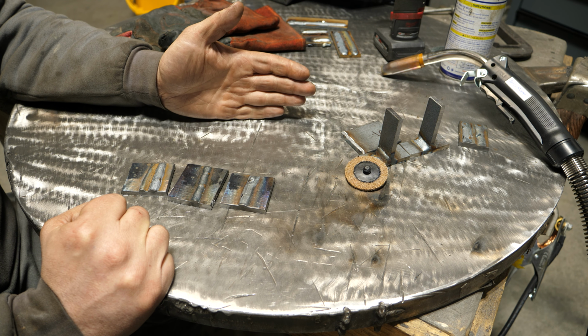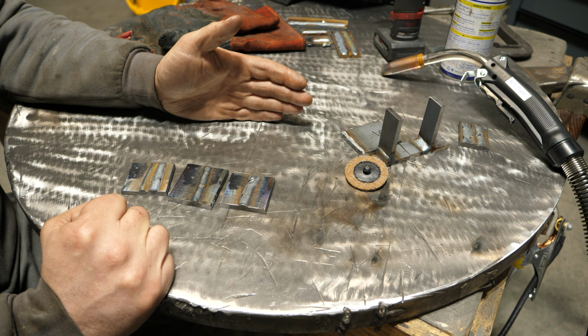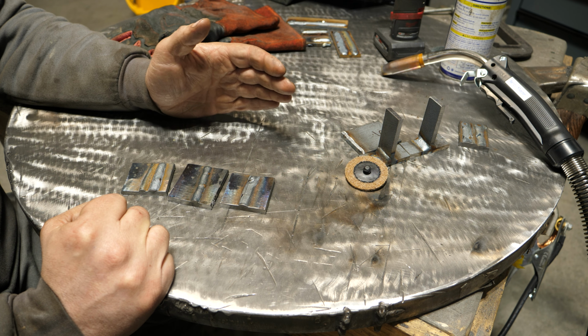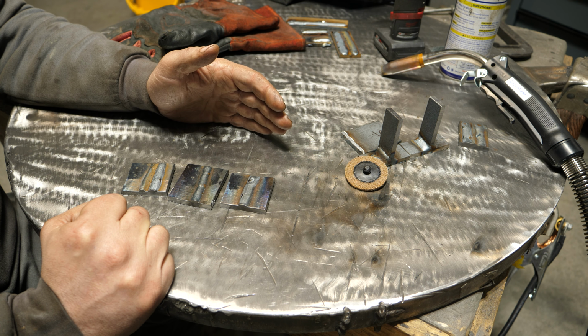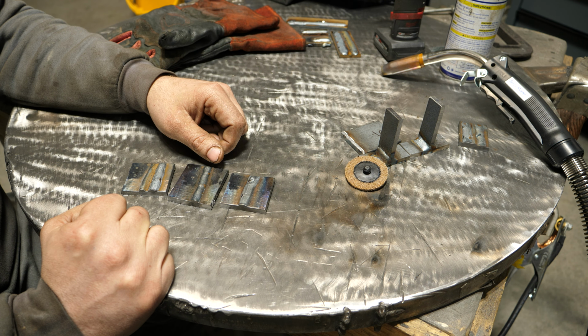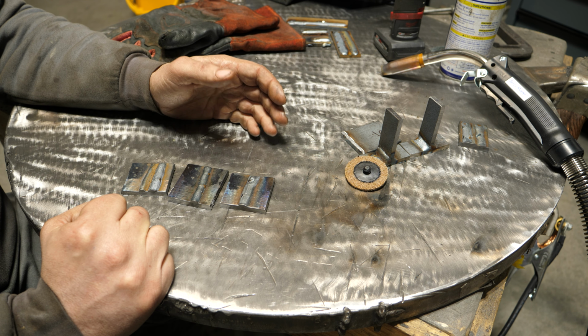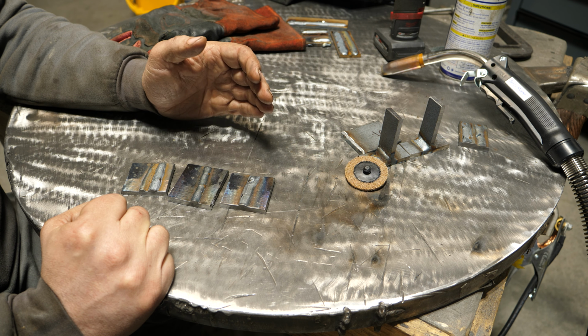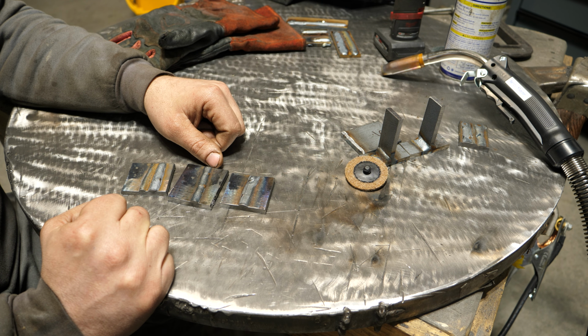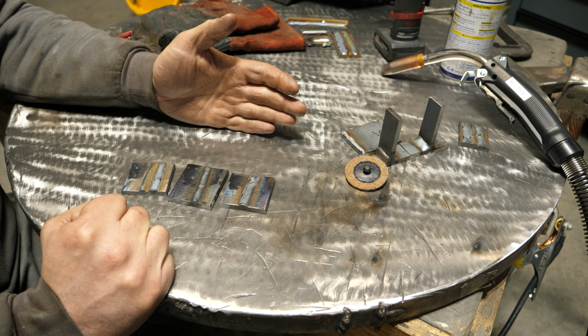Short arc sounds the same no matter what, unless you're running really bad settings. So you can't tell just by the sound or what you're seeing to what extent your fusion is, especially if you push instead of pull with short arc, where you lose fusion. That's going to be somewhat of an issue on thicker plate. So it's just a reliable way to get fusion in the primarily flat position if you can run it.